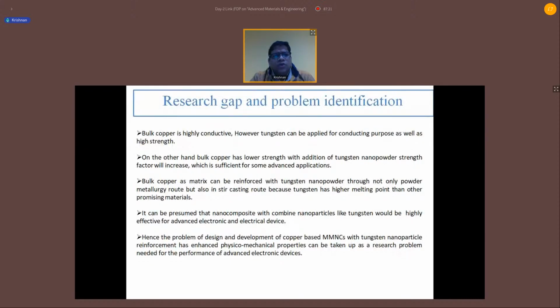Bulk copper as a matrix can be reinforced with tungsten nanopowder through not only the powder metallurgy route but also stir casting. But in our lab, in the stir casting route, the crucible size is large, and we know that when we produce any nanoparticle at lab scale, the amount is very small. So if we reinforce 5 gram, 6 gram or 10 gram, producing uniform-size nanoparticles and controlling the reinforcing properties is very difficult. So we are using pressure compaction, and after that sintering, and we got the material.